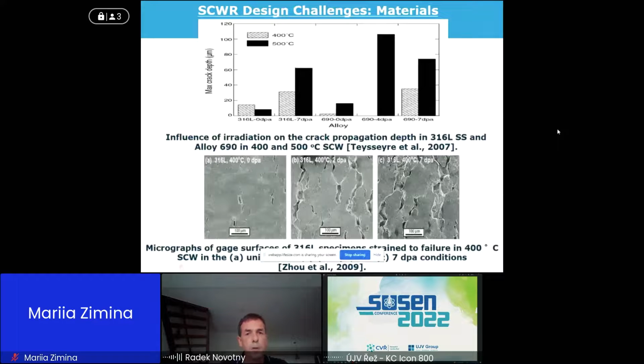Of course, the effect of irradiation is really a huge challenge because so far we haven't performed any in-pile test. We have a limited number of studies on the irradiation effect on crack propagation. Here you can see the results of one of these studies, the effect of higher DPA on maximum crack depths, which was the criterion used in these SSRT tests. And if you look at the micrographs in the lower part, you can see a huge growth in the density of these cracks based on the material's DPA.